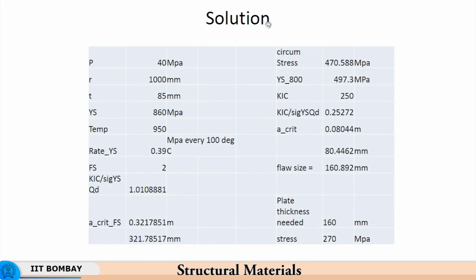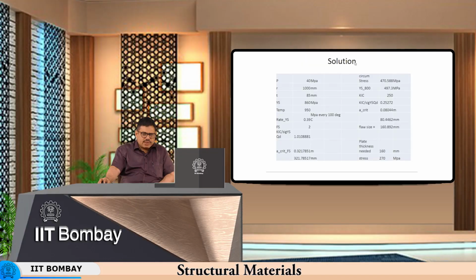So, you have this yield strength at 497.3 MPa, which is very close to the circumferential stress. So, naturally you need a factor of safety of at least 2. So, then that makes it, if you look at the critical flaw size here, it is about 80 mm. So, what it means is that the plate thickness that is needed for a leak before break phenomenon to be achieved is of the order of 160 millimeters. That is because for leak before break the critical flaw size A critical should be greater than the thickness.